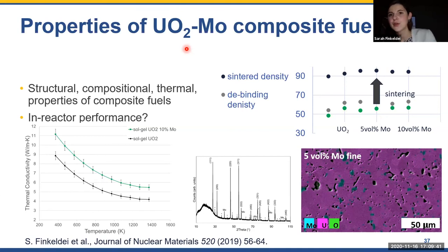Yeah. So those ones, what I did is I also started from these microspheres. And in the first round, I actually destroyed the microspheres. So we crushed them by milling them, and then we just mixed them with a molybdenum powder and cold pressed a pellet out of those. In the second step, where we are currently, we used the microspheres in the fabrication process, so what you can do is add a solid to your feedstock solution, and therefore it will be incorporated into your spheres.